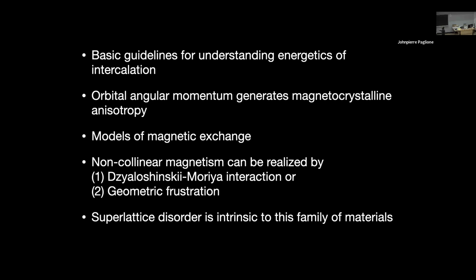Then, what we've been learning in my group about the magnetic exchange in this family of materials. They're metals, so it's presumed that the interactions between the moments would be what's known as RKKY, but it turns out that in many cases, if you actually try to interrogate that, it does not fit that model. Why is that? Then we'll explore a couple of cases where you get non-collinear interactions, not parallel or antiparallel, but maybe canting within the plane in these helimagnetic cases, or this 120-degree AFM, arising either from the non-centrosymmetric symmetry of the crystal lattice, and so the Dzyaloshinskii-Moriya interaction, or, even if we have a centrosymmetric structure, from geometric frustration. So we'll talk about that. And then finally, what I really want to share with you are some things that we're starting to understand about superlattice disorder in these materials.